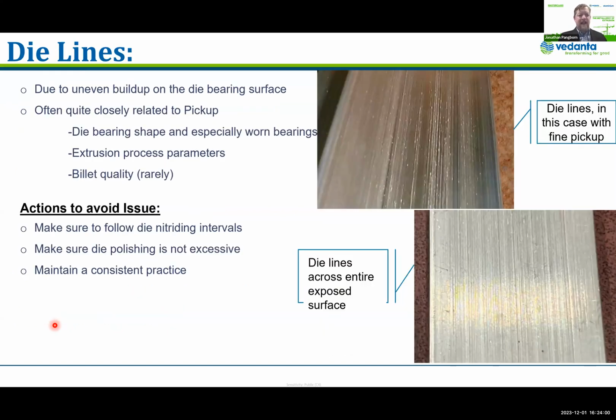Moving on here to die lines. This is actually fairly closely related to pickup, even though the appearance is quite different. In fact, in this first image, we see die lines, but we also see fine pickup that's closely associated, and maybe it's difficult to see on some screens, but you can even see that they are aligned, where the pickup is and the die line are in the same position on the part. That is not uncommon, but it comes and goes. In this example here, there's not so much pickup, just die lines on this part.